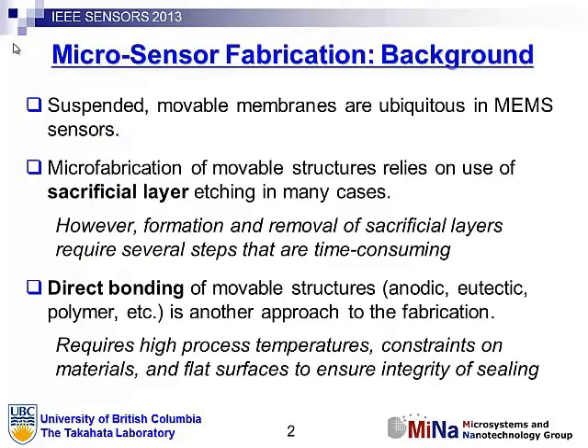Typically, when you're fabricating a capacitive pressure sensor, you want a thin membrane that's suspended above a hermetically sealed chamber so that when you apply an external pressure, the membrane deflects into the chamber and you'll get a change in capacitance if your membrane and substrate are both conductive. There are two standard techniques for making these structures. One at the bottom is direct bonding, where your membrane comes from one silicon wafer and your substrate is another wafer, say glass or silicon, and you bond them together using either high heat and pressure or eutectic bonding or some sort of adhesive bond.